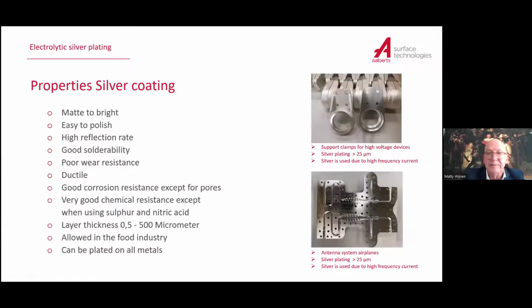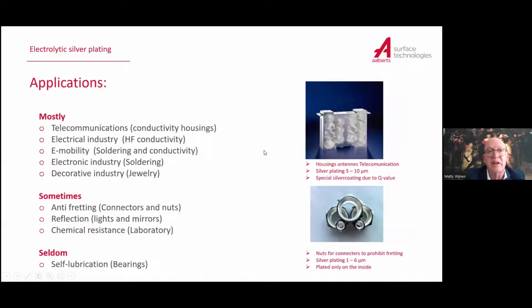Then we have silver plating, and silver plating is done for a lot of reasons. It's a noble material. I know that for some customers, it's not that suited, but it has really good properties, especially in conductivity and especially high frequency conductivities. It's used for housing antennas. In all the antennas for telecommunication, the parts are silver plated due to the fact that the signals come through with very high frequencies, and silver is purely good for that.